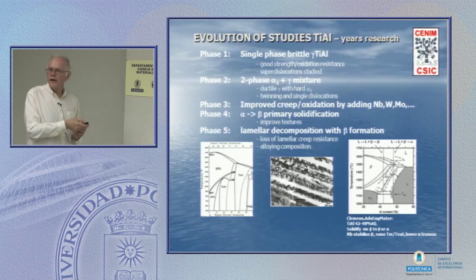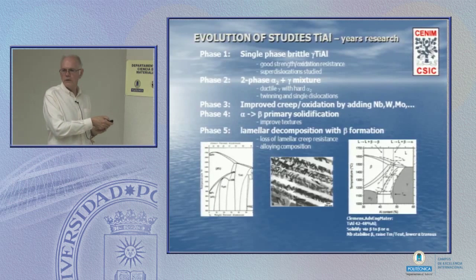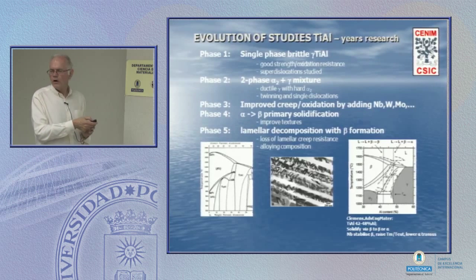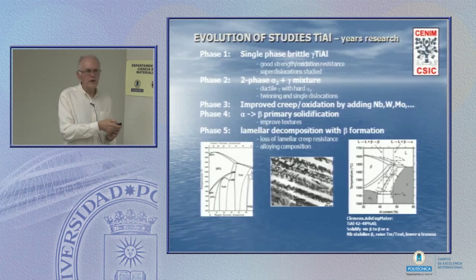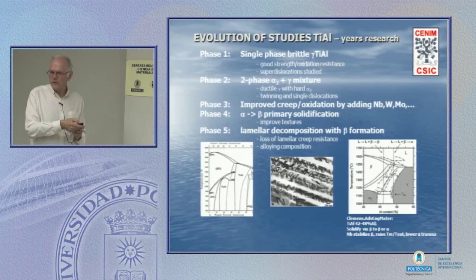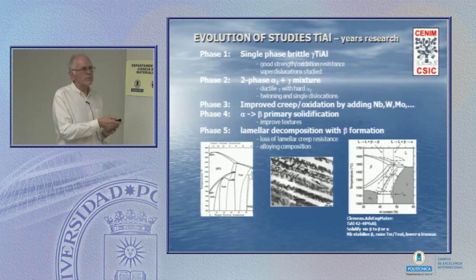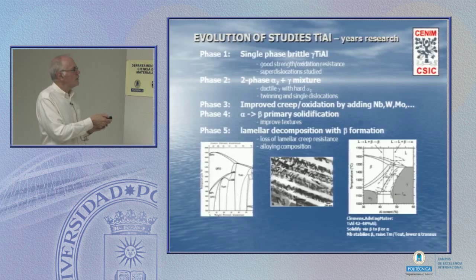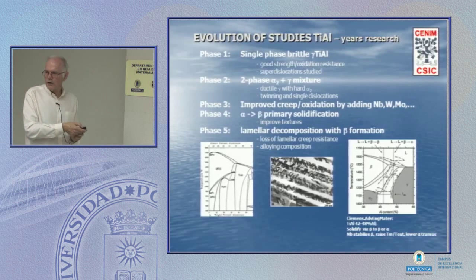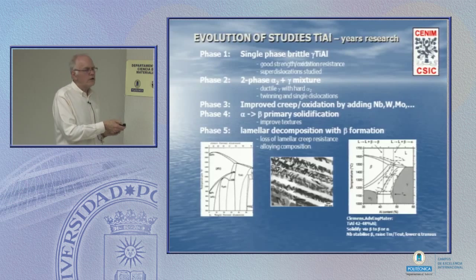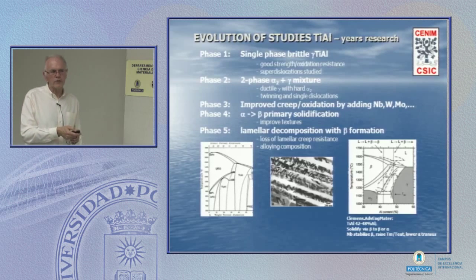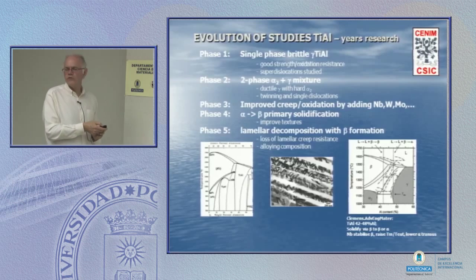Then there's this problem of the peritectic solidification. It means that the composition changes greatly within the one alloy. And that will affect, in one part of the alloy, the same component, you may be here, in another part you may be there. That's not allowed. And so adjusting the composition by careful adjustment of these, avoiding the peritectic solidification and avoiding the segregation problems that go with it. And then this lamellar structure is very often the structure that we want. It decomposes during a long time at high temperature, so the properties change, and so we have to do something about that.